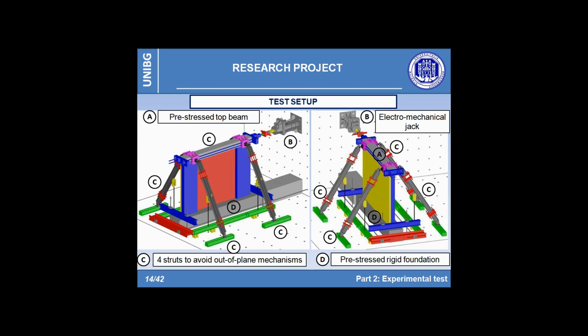To ensure that the wall deforms, avoiding lateral instability or out-of-plane displacements, a retaining system composed of 4 steel struts has been set up to guide the specimen during the load application. Letter C in the image. The rigid foundation has also been pre-stressed to prevent any possible slip phenomenon, and moreover it has been tied to the reaction floor close to the external sections, exerting a vertical confinement that inhibits its rotation and then its lifting.